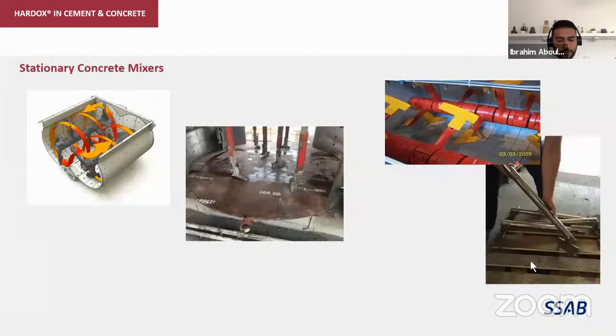For the stationary concrete mixers, more or less the liners for different types of mixers, such as planetary, vertical, and mobile mixers, can be relined by Hardox 600 right away. In some cases, if there is some complex shape, it can be from 500, but usually if there's only a little bit of roll bending or if it's flat, Hardox 600 all the way. And on the right side, you can see Hardox 600 in paddles. They are more or less 25 millimeter thick, and they are competing with the Ni-Hard materials.